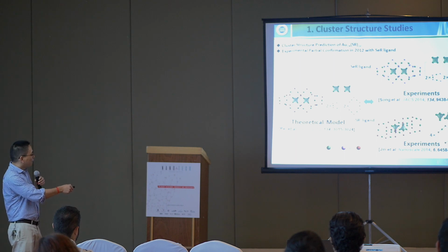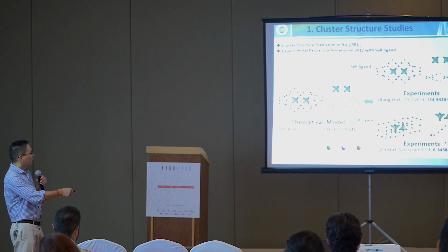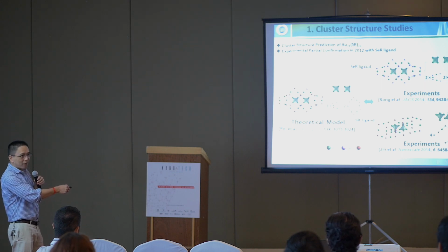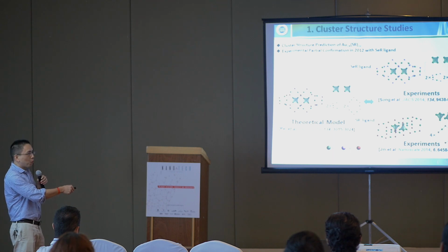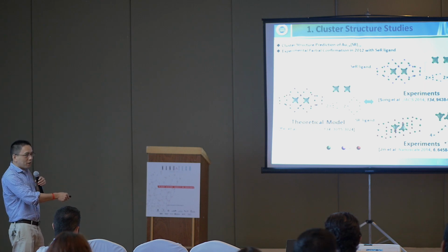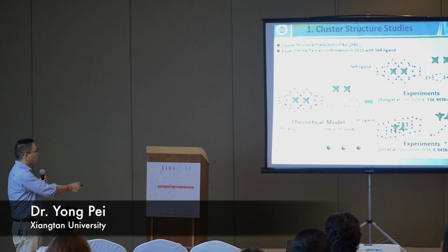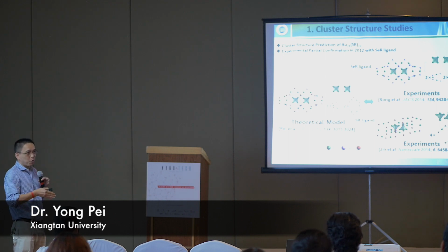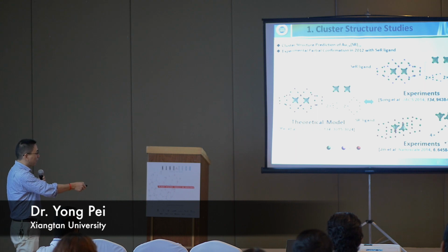The difference is, we can see this one, reported by Professor Zhu's group in China. He found that when the ligand is SeR rather than SR, the crystal structure agrees very well with our theoretical predictions. But when the ligand was switched to SR, not SeR, the structure is slightly different. So we don't understand why, because we know Se and S are in the same group in the periodic table, but they have totally different crystal structures.